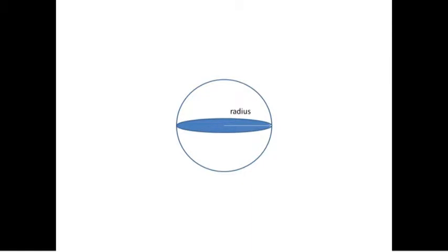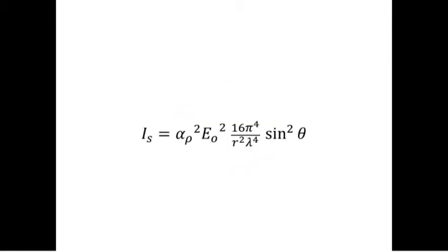Scattering intensity is a function of scattering angle, particle shape, and particle size. For this instrument's modeling, the particle shape is assumed to be spherical. The particle sizer uses the Fraunhofer model for larger, opaque, or highly absorptive particles. For the Fraunhofer theory, particles of varying refractive indices can be used because the scattering intensity is concentrated typically at angles smaller than 10 degrees.